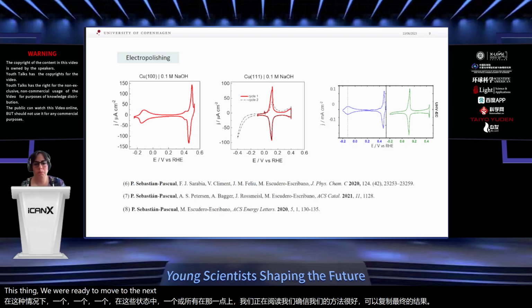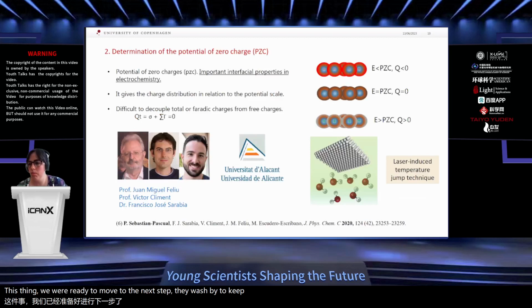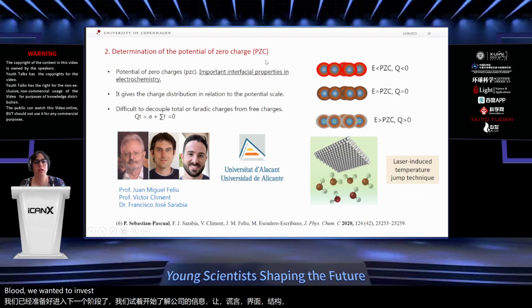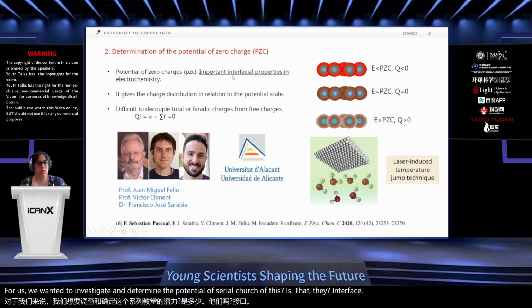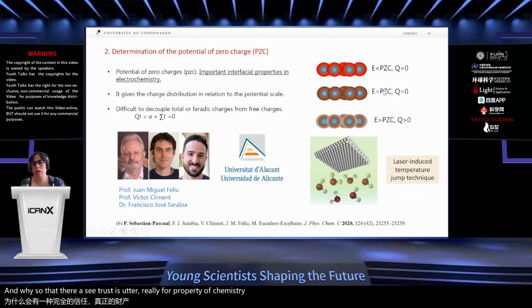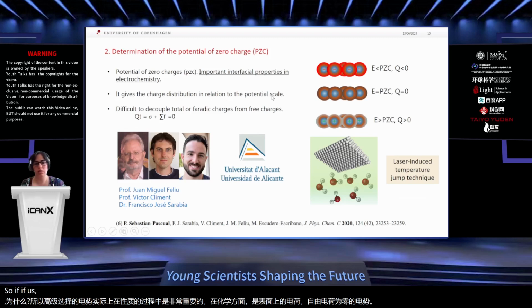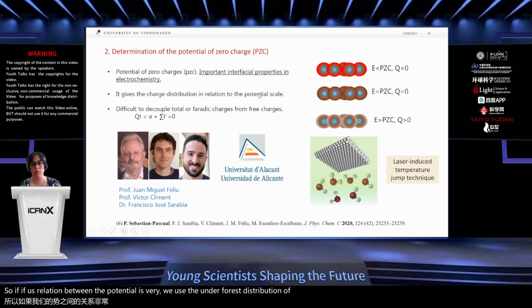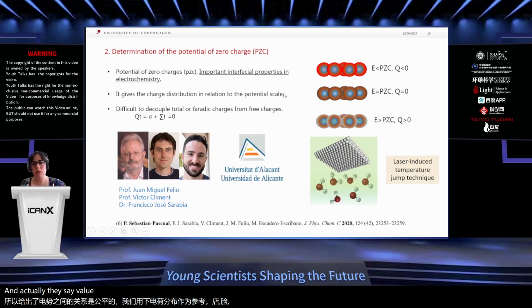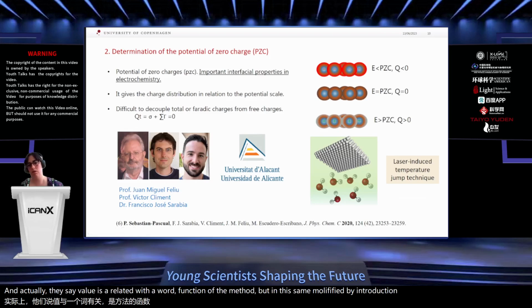That was to try to get information about the copper electrolyte interface structure. And for that, we wanted to investigate and determine the potential of zero charge of the interface. And why? The potential of zero charge is a very important interfacial property in electrochemistry. It is the potential at which the free charge on the surface is zero. So it gives us the relation between the potential scale we use, the reference electrode, and the charge distribution on the surface. And actually, this value is related to the work function of the metal, but in this case modified by the interaction of the electrolyte.